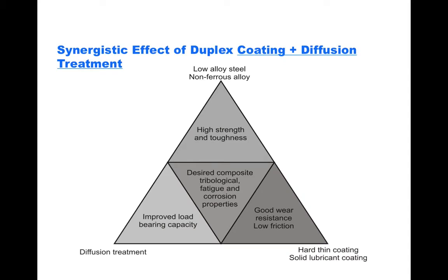So one way to represent this is that we have a diffusion treatment, say, to improve the load support. Maybe a thin film to give either improved tribology in wear resistance, or a soft lubricant film, together with a suitable substrate to combine them together. And that's what we mean by a duplex treatment. So we think there's a big move towards duplex coatings and diffusion treatments.